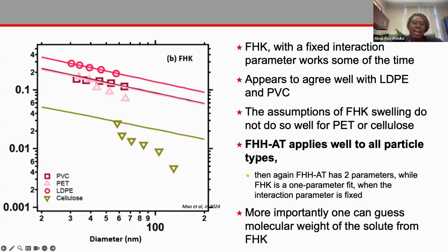So we say in this paper that you should probably apply adsorption theory, which worked well for all the products, right? But then again, how we applied adsorption theory is that there were 2 parameters. There was an A and B parameter, whereas FHK only had 1 parameter because we fixed the interaction parameter. And the key to life is the more parameters that you have, the more you can make a fit. So FHK did not fit as well because we only had 1 parameter.